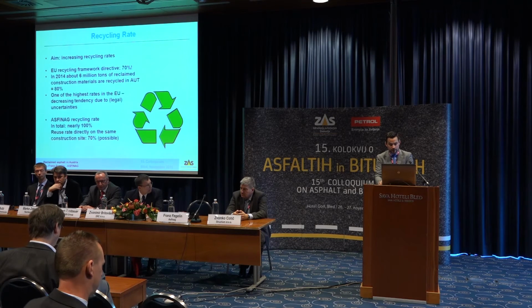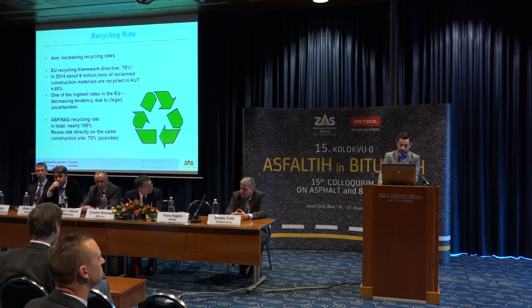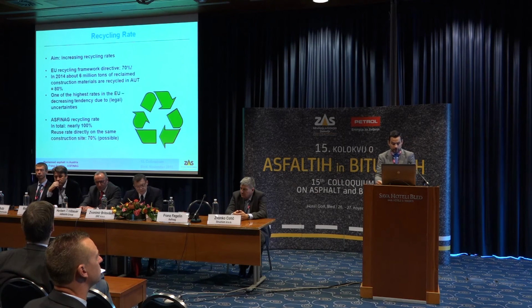So we can say that our activities serve to both increase the recycling rate and change people's view about this issue. The target value of 70% set by the EU Waste Framework Directive is being exceeded in Austria. In 2014, the percentage of reclaimed construction materials was 80%. This was one of the highest reached in the EU.